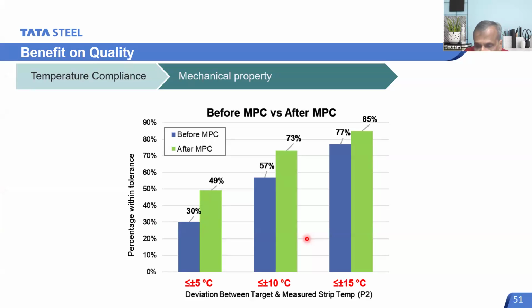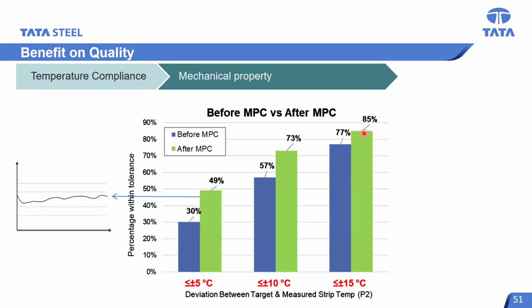This is the biggest impact on quality, the temperature compliance. We allow any element of strip which is within a plus or minus 15 degree band. But how good is the tighter control? If you look at the closest band, within plus or minus 5 degree, there is a remarkable improvement from 30% to almost 50%. On the other hand, anything beyond this plus or minus 15 degree is reject. That also has been reduced by about 8%. This has been shown here in the control charts. So this is within, and this part has also been reduced.